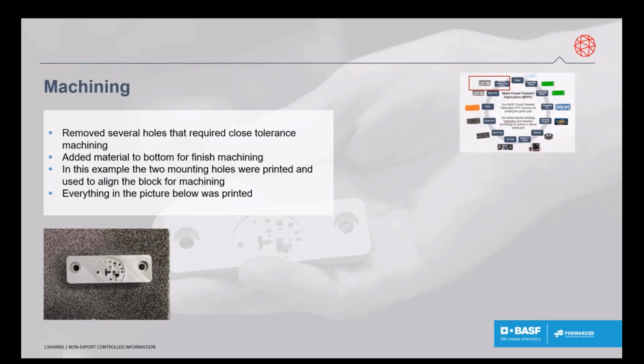This is actually one of the first complex parts that we printed. The block size is about 3 inches long by about 1 1/8 wide and 1 inch high. Those little channels you see going down into square rectangle things, they actually angle underneath. So there's all kinds of geometry going on below the surface of the part. Traditionally, this part would be sectioned and all those little shapes would be machined in individually, and then the block would be fastened together with screws and dowels. So this is a big enhancement over traditional process.